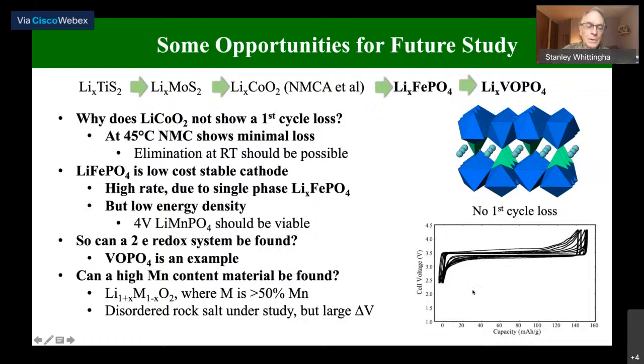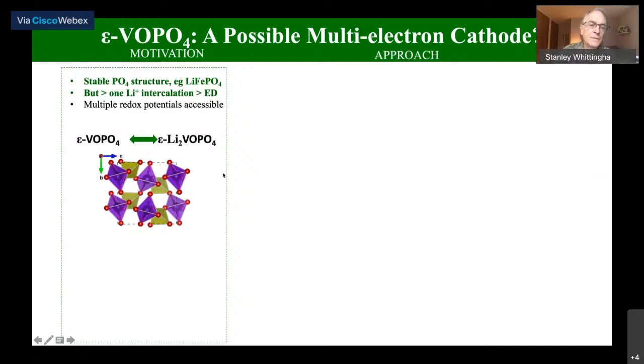So let's look at this vanadium phosphate. This material, this epsilon phase, was first formed by Alan Jacobson. It has a nice three-dimensional structure, so it should be structurally stable. The phosphate group makes it thermally stable as well. So the goal here is, can we make it an electrochemically active form?